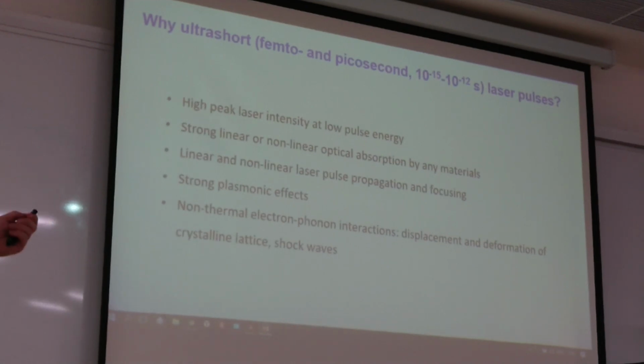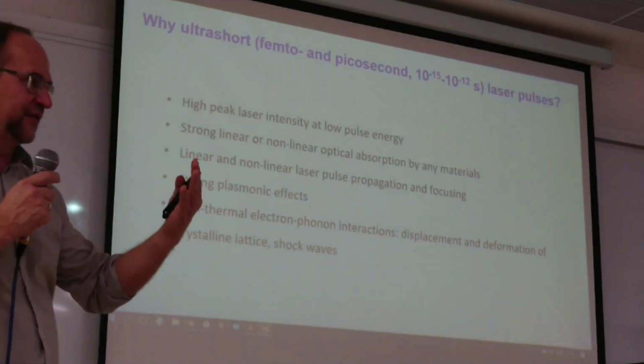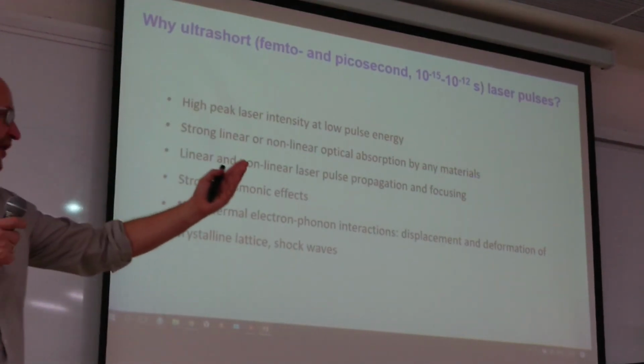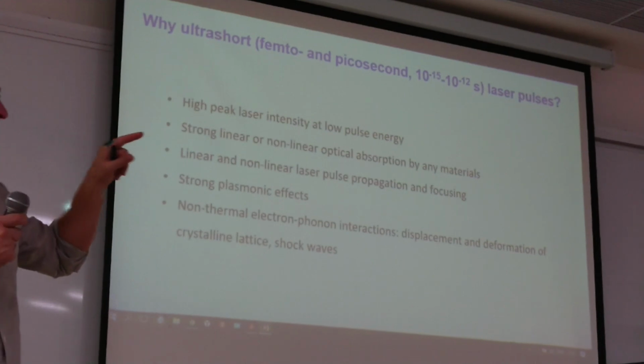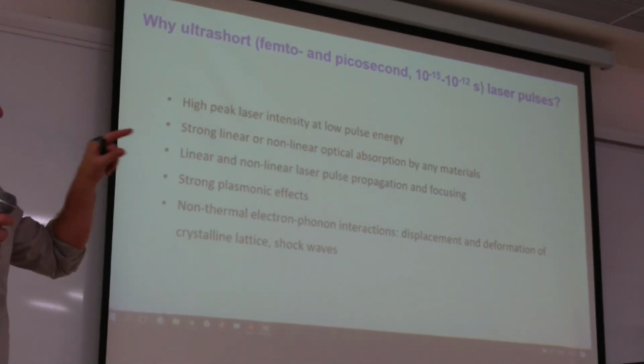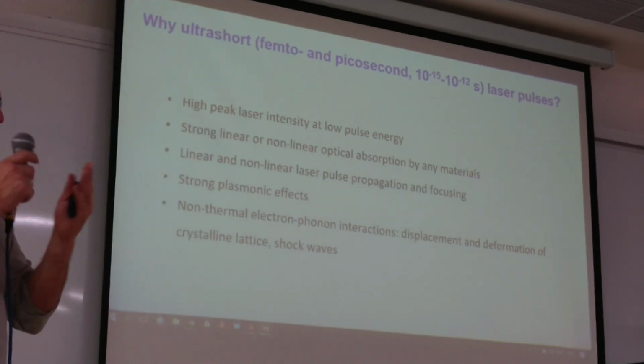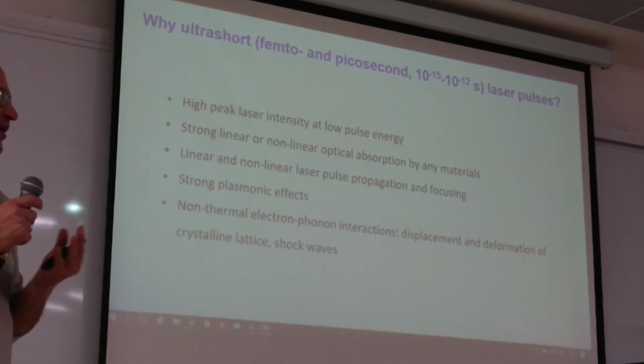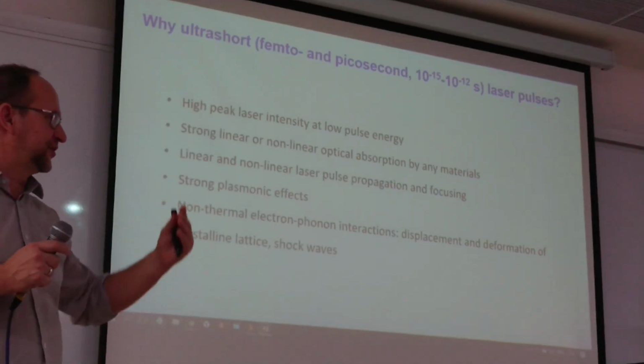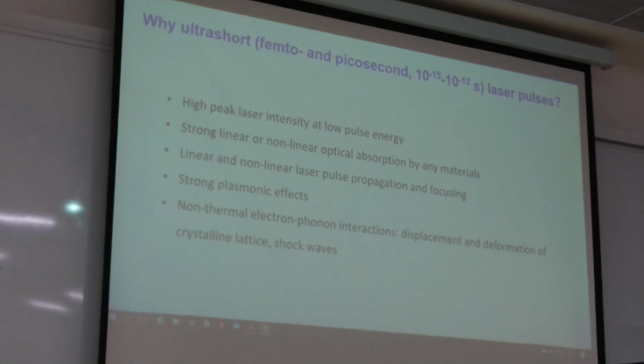Because of these very short pulse widths, we have high peak intensity even at low pulse energies. Again, because of high intensity, we have strong linear or non-linear optical absorption by any materials. So even transparent media, which are generally not absorbing at all, like window glass: if a focused femtosecond laser enters the window glass, it makes plasma, so absorbing that almost total energy can be absorbed and not go through. And this is because of very high non-linear absorption.